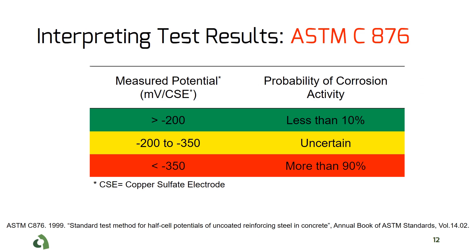For example, ASTM C876 introduces three different ranges for the measurement. Half-cell potential values less than negative 350 millivolts, measured in reference to copper sulfate electrode, represent an area where probability of having active corrosion is more than 90%.